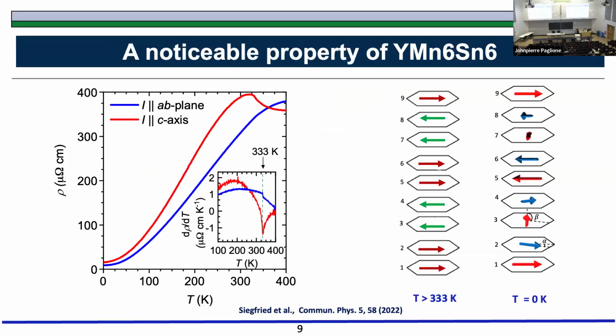With this, then we observed another very interesting property. It may not be interesting if you look only at this compound, but I will try to make it interesting when we start tuning these properties and see how this evolved. Just remember that there are two measurements here. What we are measuring is electrical resistivity, simple. In the red one we are passing current along this direction. In the blue one we are passing current along this direction.